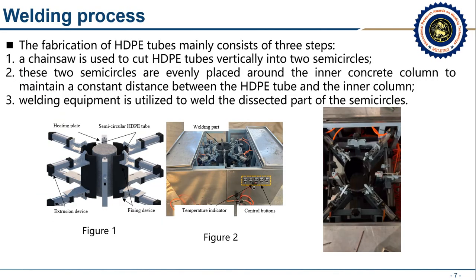The fabrication of HDPE tubes mainly consists of 3 steps. First, a chainsaw is used to cut HDPE tubes vertically into 2 semicircles. Second, these 2 semicircles are evenly placed around the inner column to maintain a constant distance between the HDPE tube and the inner columns. The last step is welding equipment is utilized to weld the dissected part of the semicircles.